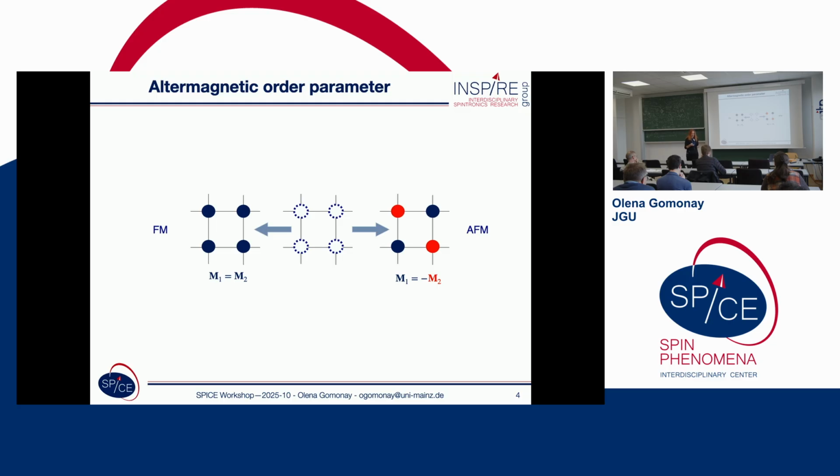Our idea is not to go in one dimension, where we have only this magnetic ordering. We suggest to introduce another dimension in the phase diagram. Let's imagine that we start from some paramagnetic state which has a spherically symmetrical magnetic environment. Then, in principle, we can imagine a kind of transition which prepares a lattice to be altermagnetic. So no magnetic ordering at all, but there is something which distinguishes these fully symmetric S-type structures from those which would then be altermagnetic.